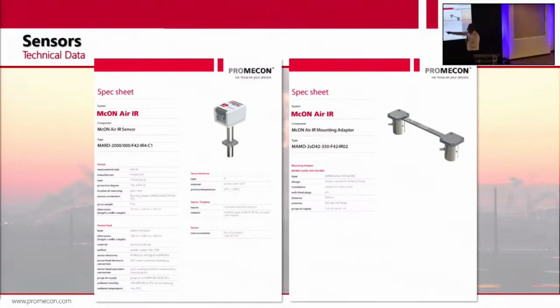One thing interesting, this is not a long sensor. This is a sleeve, and there's an infrared diode on top of here. That's our new wonder sensor. We can measure the velocity, but we could also measure chemical composition. And chemical composition is not, like Durac said, down to ppm, ppb. This is the other end. We are measuring percentage. We're measuring 20% CO2, 30% CO. When you have a steel furnace and the temperatures are so high, all the CO2 falls into CO because the high temperature destabilizes the molecules. So you have excessively high CO. You want to know the CO and the CO2 to make the carbon balance. So this is what we use this for.